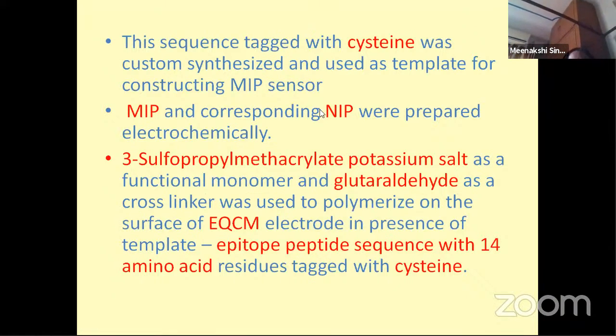By commercial companies, we designed that. This work is unpublished, so I am not detailing the sequence. It has been submitted to the journal. So without giving the sequence of the epitope peptide, what we did, we tagged a cysteine amino acid at the end. Cysteine has sulfur, and sulfur does thiol chemistry, which is very good for development of a self-assembled monolayer on a gold surface or silver surface. So here we have exploited that thiol chemistry, and this peptide sequence tagged with cysteine was custom synthesized by a commercial supplier and used as template for constructing MIPs itself.